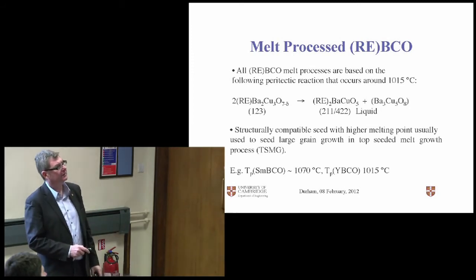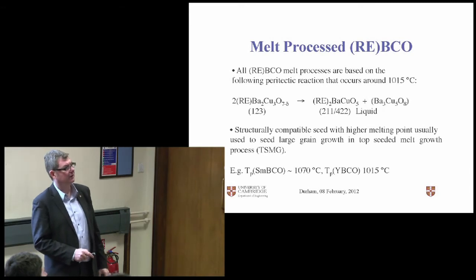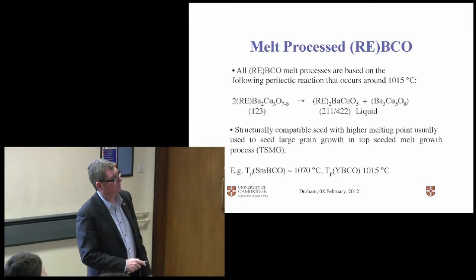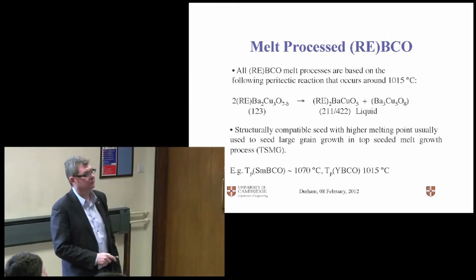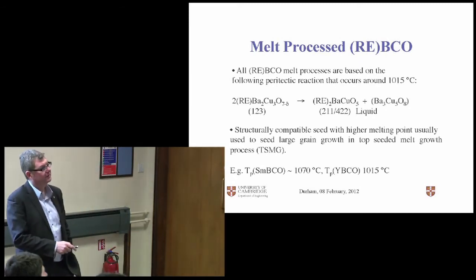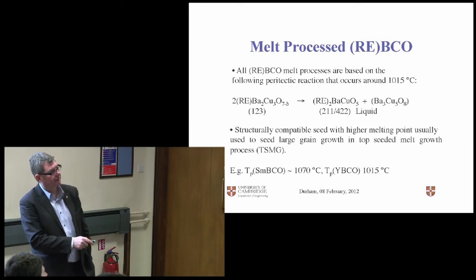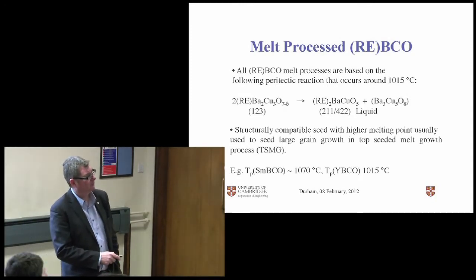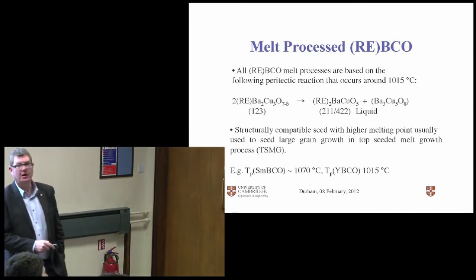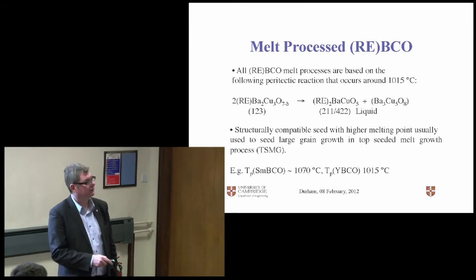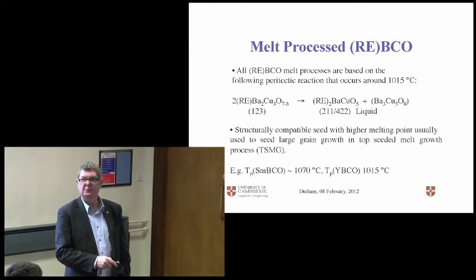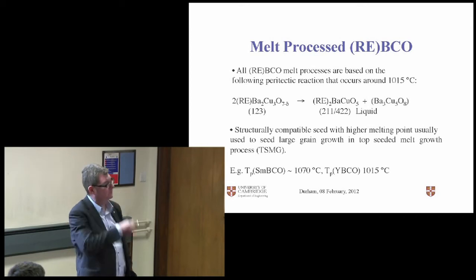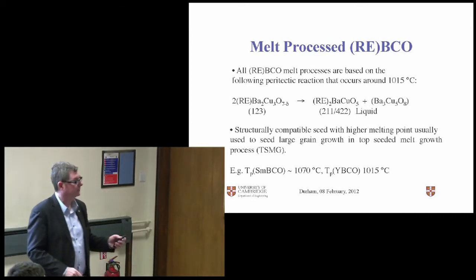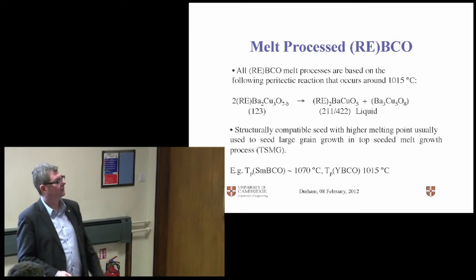Well, it's when one solid decomposes to form another solid and a liquid phase. So in this case, we have the superconducting phase, the rare earth 1 barium 2 copper 3 phase, known as the 1,2,3 phase, decomposes to form a second solid, the rare earth 2 barium 1 copper 1, which is the 2,1,1 phase, and the balance of mass gives us a barium cuprate liquid. So we then take a structurally compatible seed with a high melting point, we put that on the molten mix, and then we cool slowly back through the solidification temperature, and that gives a single grain that we can nucleate in a controlled way, heterogeneously, and grow.